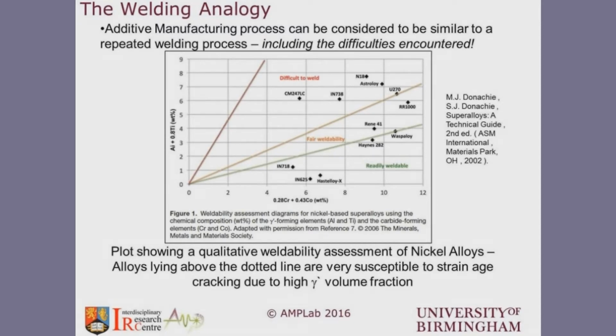On the x-axis, you can see the chromium and cobalt as one factor. There's an equation here, 0.28 chromium plus 0.43 cobalt on the x-axis, and then the aluminium and titanium on the y-axis, which are actually the elements that form the gamma prime phases.